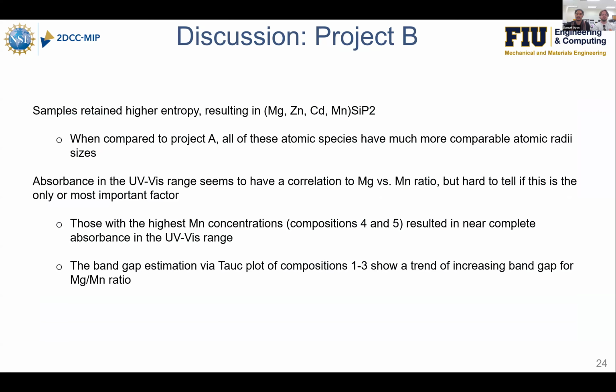Another thing we also suspect may be a contributing factor for the higher entropy phase incorporating or crystallizing a bit better is the fact that we're just working within the transition metal side of the periodic table. So the atomic radii difference is not as great with respect to the alkali earth metals. If I'm remembering correctly, the greatest difference is about 10 or 15 picometers. So there's not as much great disorder that allows for these crystals to crystallize in the high entropy phase.